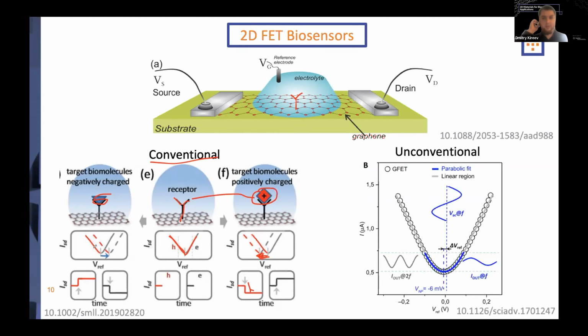If we look into an unconventional approach, you can actually utilize the so-called frequency doubling phenomenon, which is commonly used in RF applications, but you can do this in liquid. In addition to applying a DC potential to the gate, you can apply an AC potential to the graphene transistor with, let's say, a frequency of 2 Hertz here. But because you're sampling over the Dirac point, you're actually going up and down twice as often. So your output frequency is actually twice higher. And when you have a shift of the Dirac point a little bit, you're way more sensitive to the shift of the Dirac point in this case than in conventional biosensing.